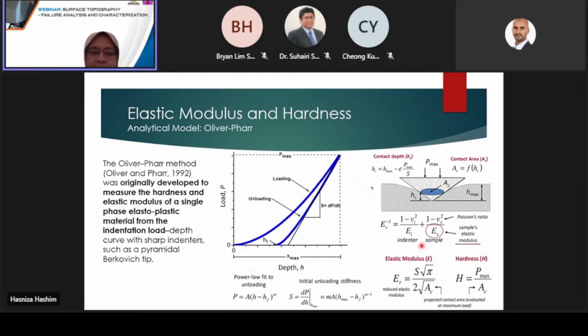In an actual nanoindentation experiment, we can calculate modulus and hardness based on stiffness and contact area at the maximum force. So reduced modulus would simply be half of the square root of pi times the measured stiffness divided by the square root of the projected contact area. And then the hardness is simply equal to the max force during the experiment divided by the projected contact area.